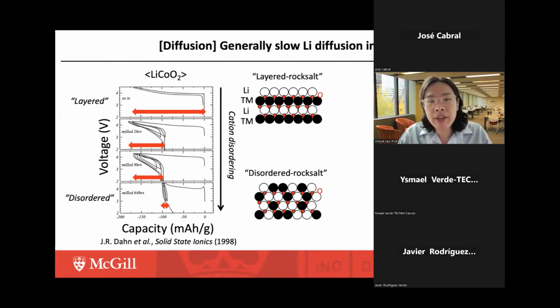And people have been explaining this poor performance of the disordered materials with a slow lithium diffusion process in the structure. People have argued this happened because with the cation disordering, the lithium diffusion barrier dramatically increases such that the lithium diffusivity exponentially decreases. Also, people have argued that the randomly distributed transition metal cations in this DRX structure can physically block the lithium diffusion path as well.